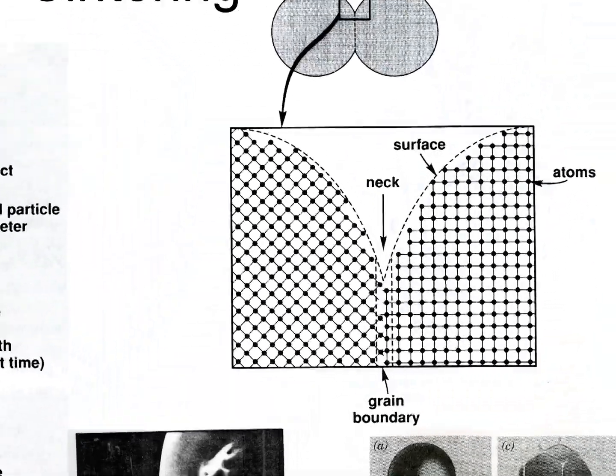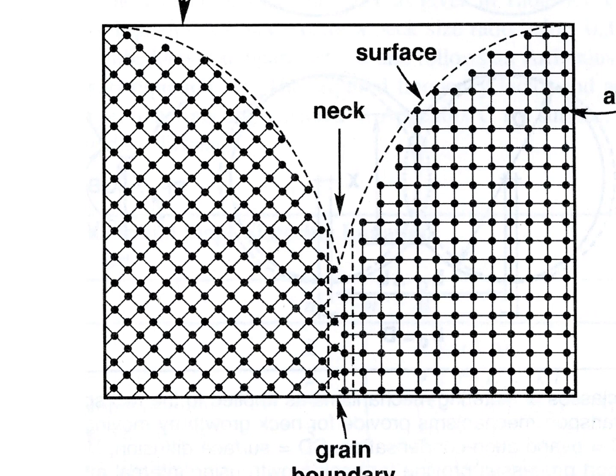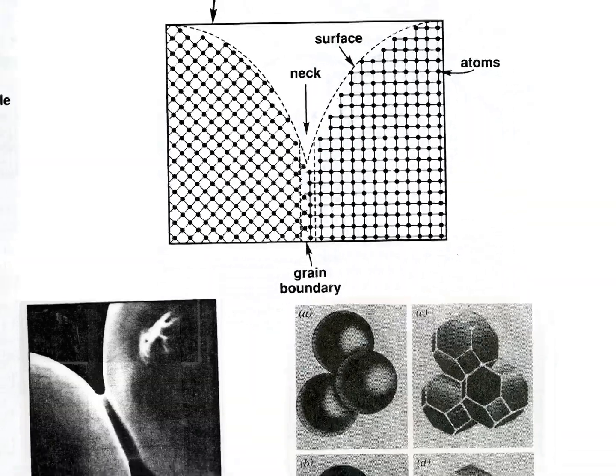And keep in mind that, again, if each of the particles is a single crystal, which is not always the case, but does happen, you have one lattice with atoms arranged in one 3D array looking at a second lattice that's arranged in a different orientation. It's the same crystalline lattice of the same material, but because they're oriented differently, you must have a grain boundary show up between them as soon as that neck forms. All right? Make sure you are totally aware of that.